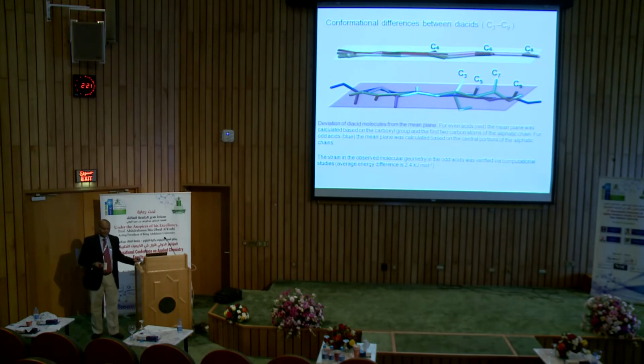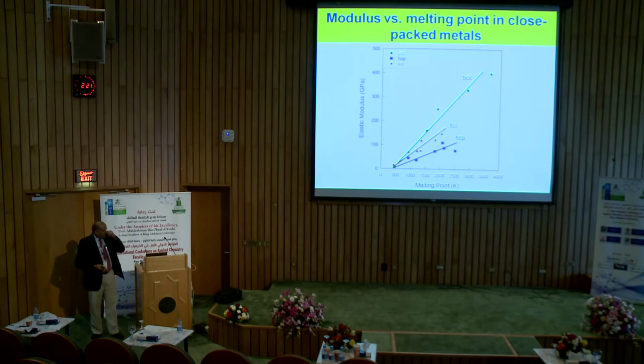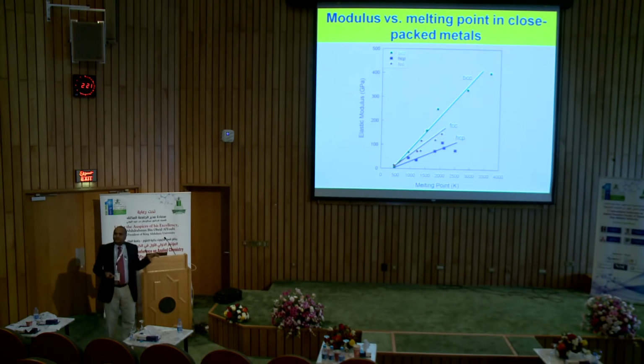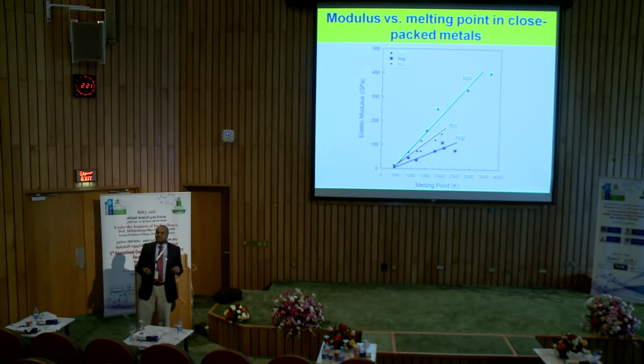Now why that reflects in melting point alteration is because when you have this, there is already strain, so they melt readily. Now, I am a metallurgist, as I told you earlier, so we know very well that for a given crystal structure, the melting point and elastic modulus are correlated linearly. This is because they both depend on the same factors, namely crystal structure and intermolecular interactions, atomic bonding.